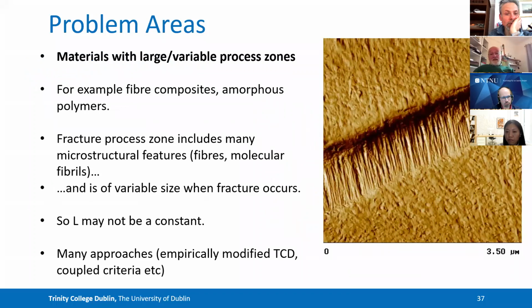There are problems in materials that have large process zones. Some materials, the process zone is similar in size to the microstructure, like the grain size, but in others, it's much larger, where a lot of microstructural elements are involved. And in those cases, it may well be that a constant critical distance doesn't always work. And again, these coupled criteria are one way of getting around that. There's certainly more to do there.